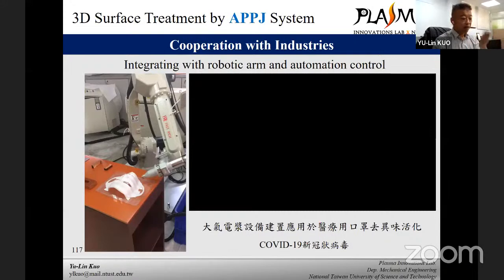Another issue is that some substrates have a very low surface free energy, because of oil or contamination on the surface. So if you use the plasma, you can do some kind of combustion or oxidation process on the surface to burn out the oil-based contaminants. So the surface will become more active. So that is the answer to the first student.